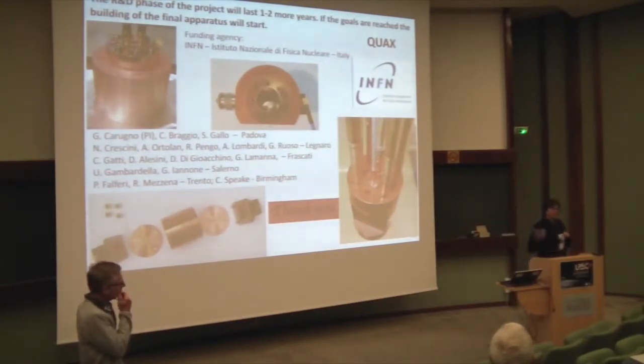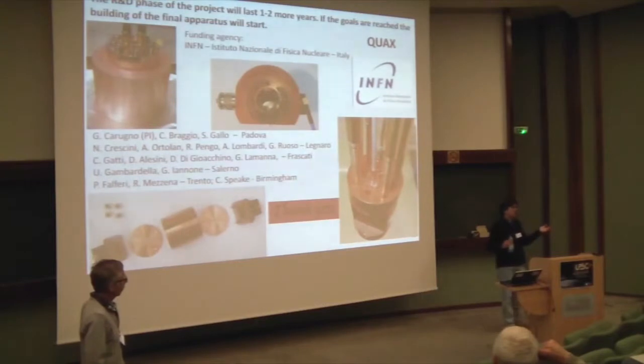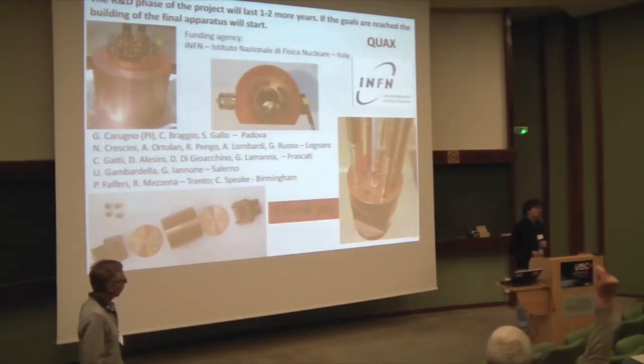So we believe that this is a good idea, and if we find the right alloy for the sputtering, then we can really get up to 10 to the 6 Q factor in the field, which is not a strong field for us. We don't need to go, of course, to 7, 8 Tesla, because even if we run at 48 gigahertz, this will be 1.7 Tesla. And there we hope that the degradation of the Q factor is not so strong for this type of material.